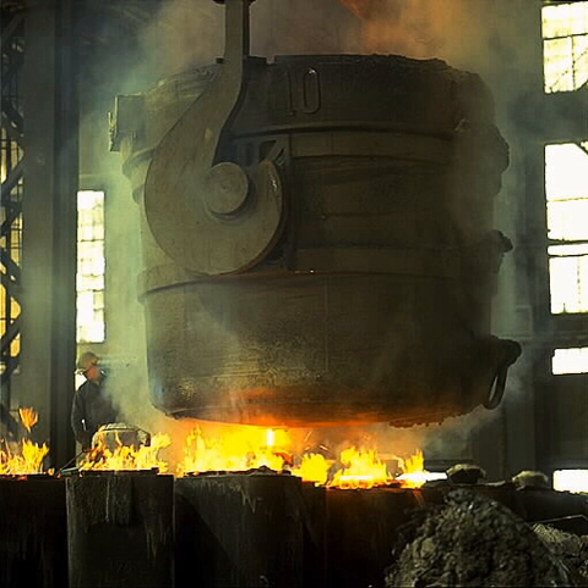In malleable iron melts, bismuth is added, on the scale of 0.002 to 0.01%, to increase how much silicon can be added. In white iron, boron is added to aid in the production of malleable iron. It also reduces the coarsening effect of bismuth.